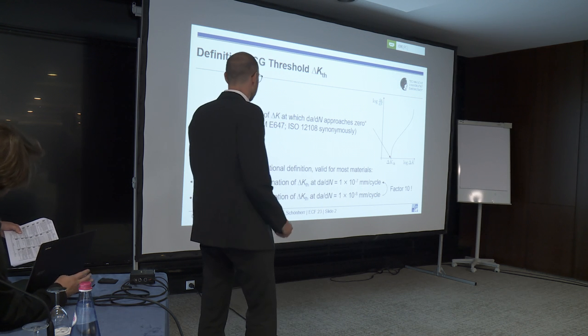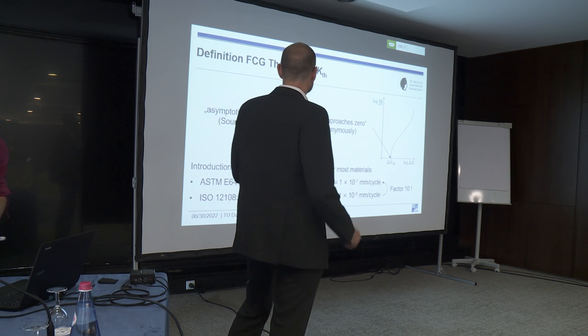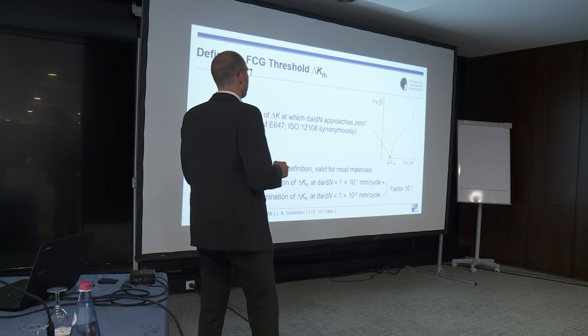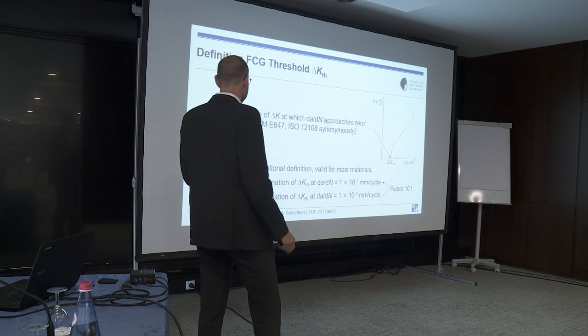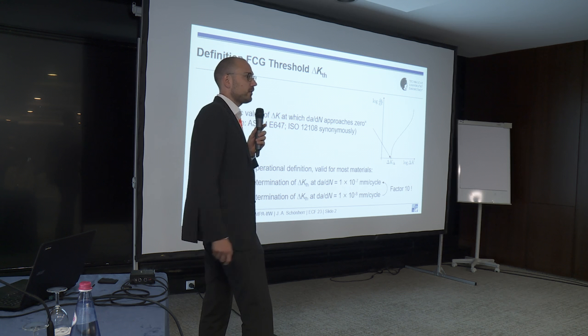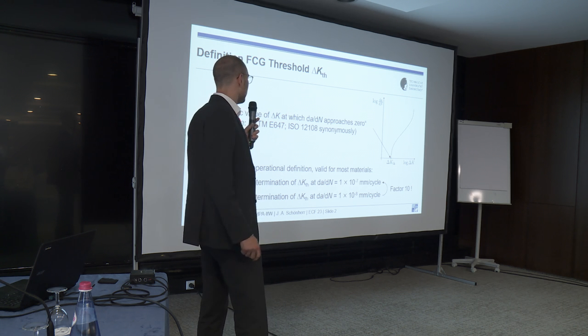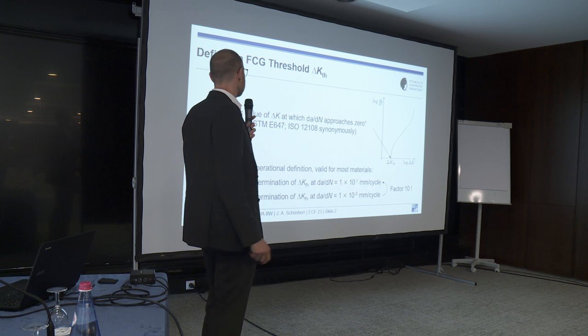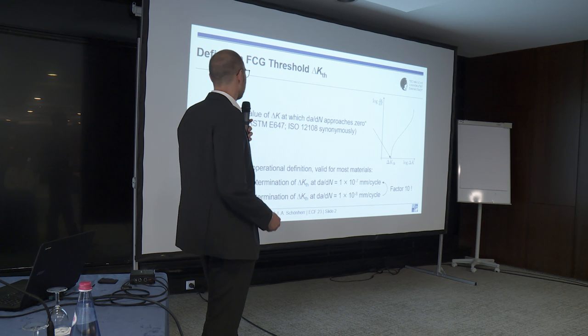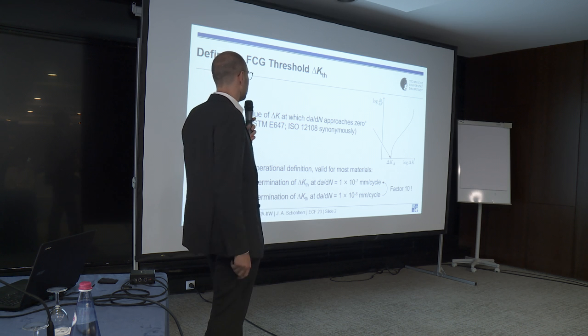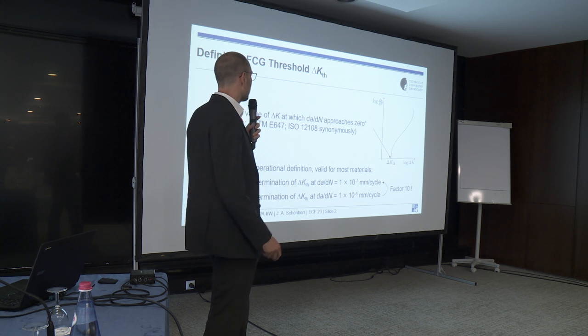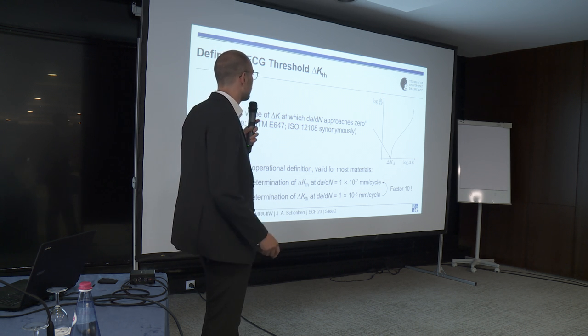We are talking about the fatigue crack growth threshold, which is usually abbreviated as ΔK_TH. According to the ASTM standard for fatigue crack growth testing, the fatigue crack growth threshold is defined as the asymptotic value of ΔK — that's the load value used in linear elastic fracture mechanics — at which the crack growth rate da/dN approaches zero.